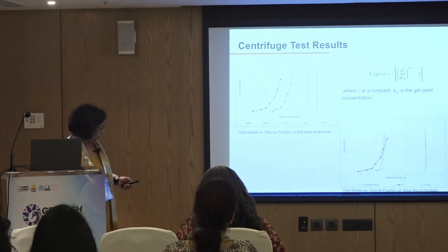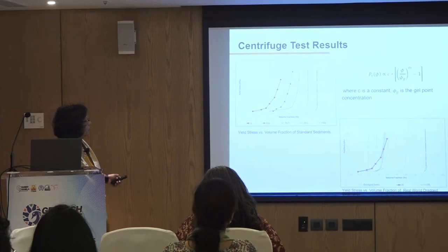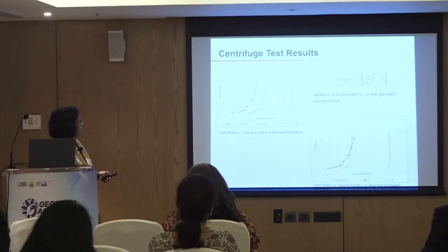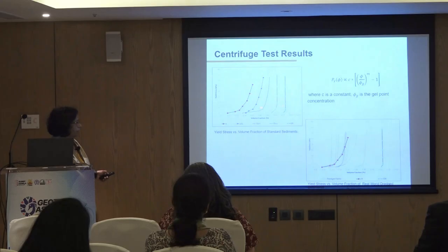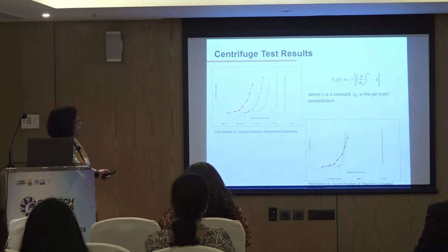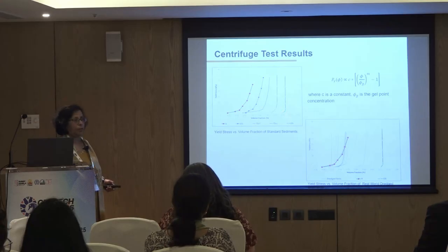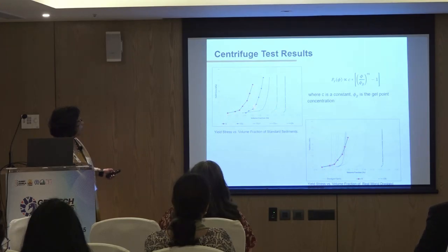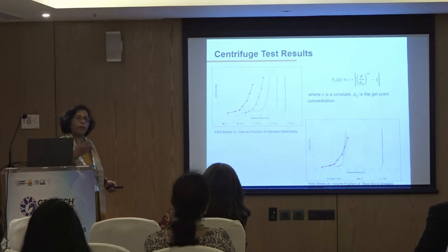So here I show you results for the standard 5 sediments, where kaolinite is here, and then organic silt is here, which is standard, and then these are two fine silt sediments and Ottawa sand. You can see as the particle size is increasing, these curves are shifting this way, which means that after dewatering, if we start all the sediments at 10% solid, sand definitely is going to dewater to a very high percentage solid, almost 60% solids after dewatering. Whereas kaolinite, after centrifuge or dewatering, will be only 35%. But for that, we have to do the test.